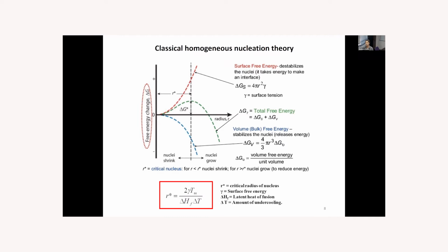So what is the homogeneous nucleation of water? The classical homogeneous nucleation theory is based on the Gibbs free energy, which is governed by two different processes. First of them is the surface free energy. This is the energy that is required in order to form the surface, and it's always positive because it needs energy for the surface to be formed, for the ice nuclei to be formed. And then there is a second competing effect, which is a volume bulk free energy, which stabilizes the nuclei. And the total free energy is the composition of these two effects.